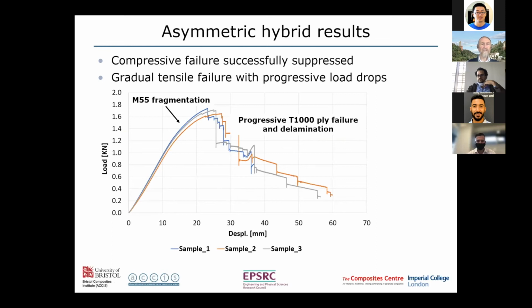So first of all, this was very successful in suppressing the compressive failure. We did not get any compressive failure at all. And we did see a very nice gradual tensile failure with progressive load drops. And what you can see on the response here, the load displacement response, is that we're getting a change in slope here due to the fragmentation of the M55 in tension. So that's gradually fragmenting up to the point here where finally we reach the T1000 failure strain on the tension side, and the first T1000 ply fails and then it delaminates.